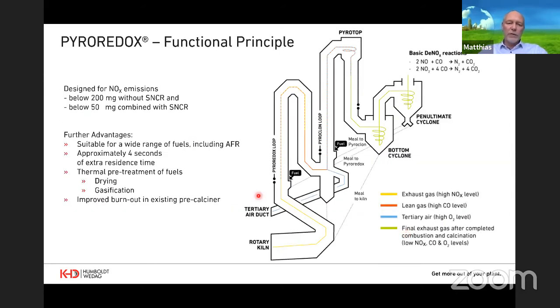Pyro Redox, as you see here, acts like an upfront extension of the calciner, where we connect the kiln exit gas into this Pyro Redox loop, and then later on mix tertiary air into it and have the regular calciner. This simple process design allows for very efficient reduction of NOx in the kiln, and also provides a lean gas that is easy ignitable later downstream in the calciner loop. Together with the Pyrotop mixing chamber, we dissolve all CO strands and run into the preheater system with a low NOx level and a low CO level.